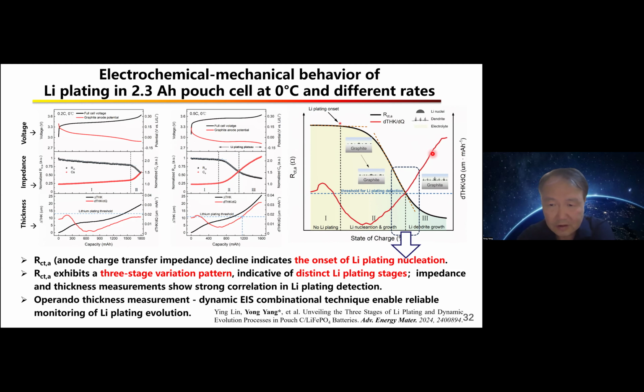You could understand that after a large amount of lithium dendrite forms, the surface area doesn't change a lot, so you cannot see that linear change of charge transfer resistance with the amount of lithium plating. But at this time, the volume change becomes more distinctive.